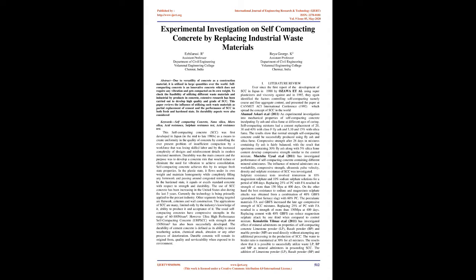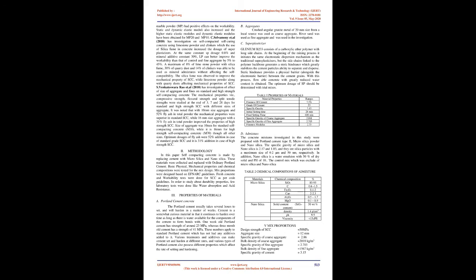Admixtures et al., 2011, an experimental investigation into mechanical properties of self-compacting concrete incorporating fly ash and silica fume at different ages of curing. Self-compacting mixtures had a cement replacement of 20, 30, and 40% with Class F fly ash and 5, 10 and 15% with silica fume. The results show that normal-strength self-compacting concrete could be successfully produced using fly ash and silica fume. Compressive strength after 28 days in mixtures containing fly ash is fairly balanced, with the result that specimens containing 30% fly ash along with 5% silica fume content develop compressive strength similar to the control mixture.